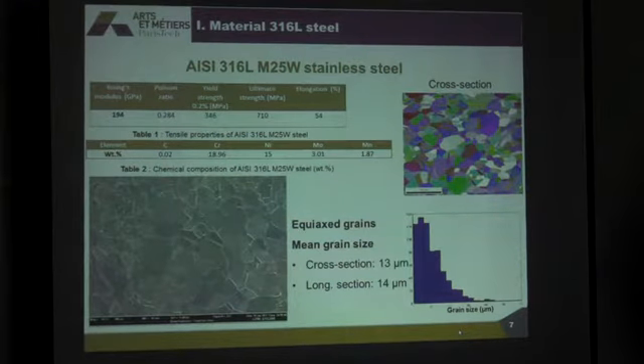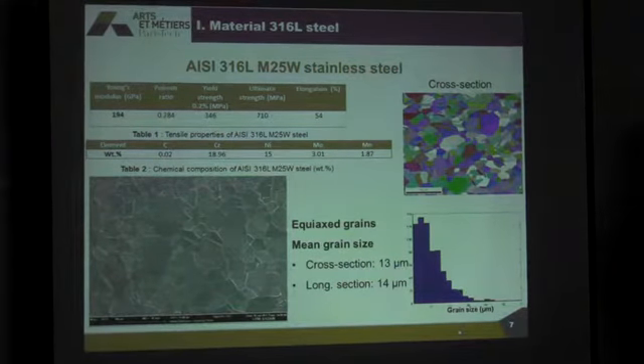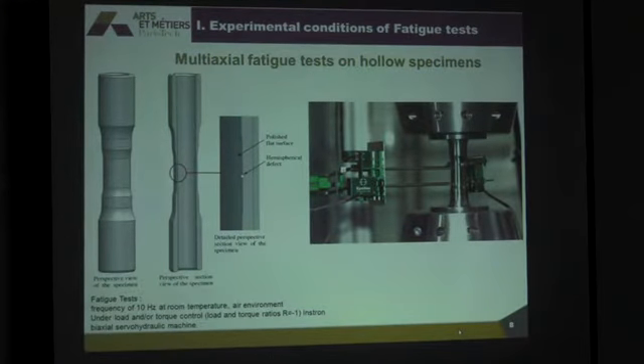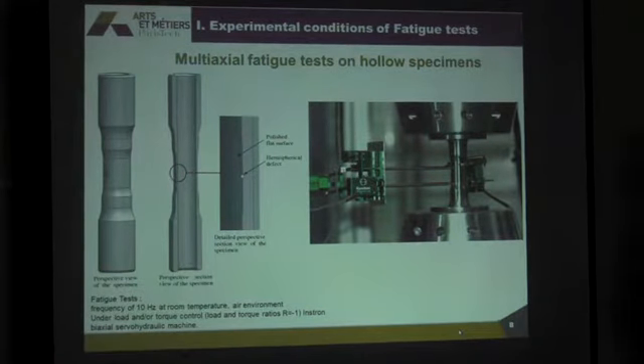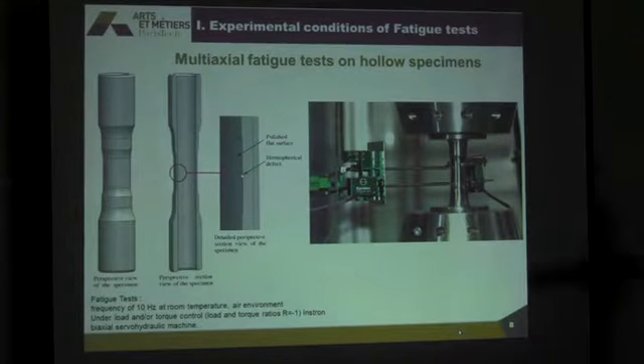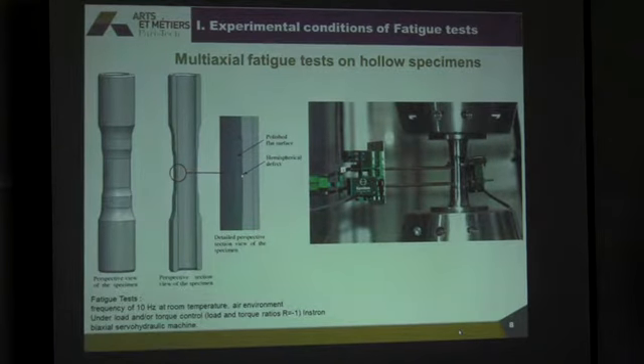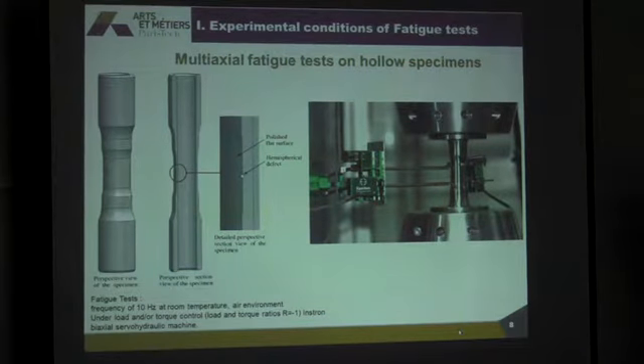We have a mean grain size of around 14 micrometers and some equiaxed grains. All the fatigue tests have been conducted on the tubular specimen that you see here. All the fatigue tests were conducted at 10 Hz, at room temperature, and in air environment. On each specimen, we polished a flat surface. And on some specimens, we introduced, via electric discharge machining, a semi-circular defect.